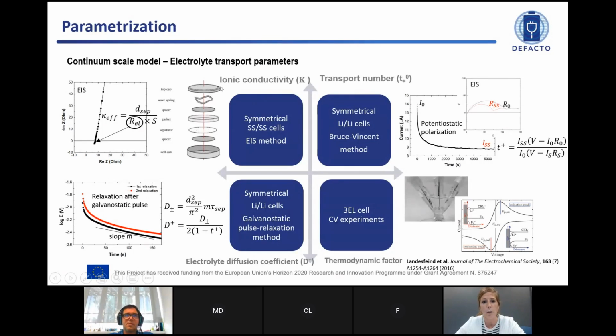So for instance, if we look to the ionic conductivity, we need to assemble symmetric stainless steel cells, and then we perform the EIS measurements. For the transport number, we need to assemble a symmetric lithium-lithium cell, and we rely on the Bruce-Vincent method. Basically, it is a potentiostatic measurement combined with the EIS spectra. For the electrolyte diffusion coefficient, we need a symmetric lithium-lithium cell, but in this case, we run a galvanostatic pulse relaxation, and then we get the electrolyte diffusion coefficient.